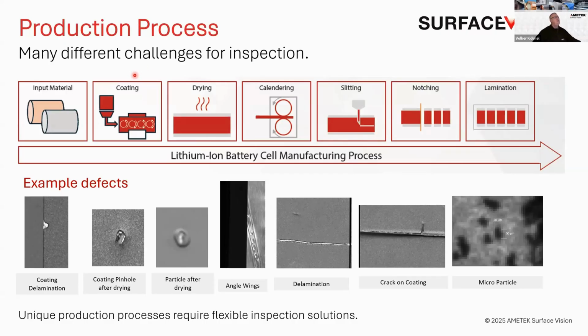So on the coating process, you have different line speeds. Then on the calendering process, you are interested in different defects, maybe on the coating, maybe defects that were applied on the coating. Then it can make a difference if you would like to inspect it straight after the coating, where the surface is quite wet, or you would like to inspect something after the drying. So this is one process typically to find defects when the solvent has left the coating and you have a reduction on the thickness. All of a sudden, you probably will see issues on particles and other defects, which were caused by imperfection of the slurry, for example, or you have kind of coating pinholes to the substrate and so on. Then the question is, is it a single side coating or double side coating? So there's a lot of questions. We have to look into it to define the challenges of the inspection system.